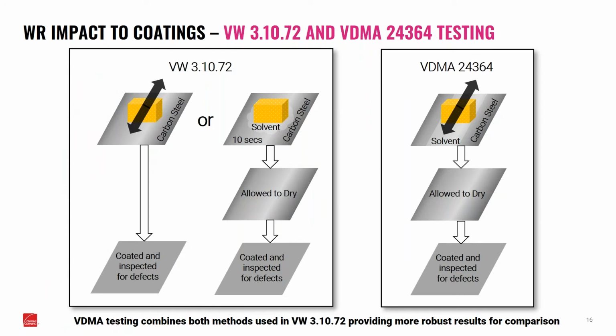So what is it about coating adhesion? One of the things that you'll see in specs is there'll sometimes be a requirement that the waterproofing agent will not contain silicones that could impact the potential for coatings to bond to a substrate. And usually that's a coating you would apply to a pipe, probably a carbon steel pipe. Now, one of the problems is when you use a silicone and you spray it on the surface of your insulation, it can also impact the way that pipe coating is going to bond to that pipe. And what you'll see is these little pinholes where that coating doesn't flow properly over the surface of the pipe.